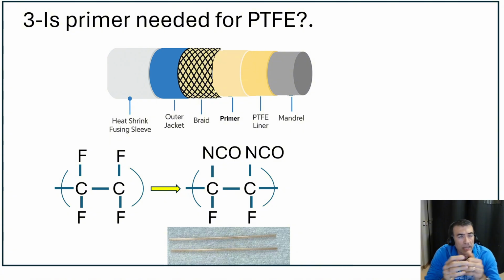And so you leave behind two active radical carbon atoms there. Over time, these carbon atoms can react with the oxygen, and therefore the etching properties of PTFE could be affected. In most cases, a primer like a polyurethane-based primer would be used, and what it would do is that this functional group of the primer would react with that radical atom and basically create a functional group on the surface of PTFE.